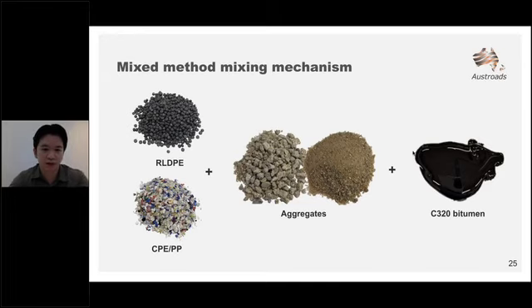Anyway, I'll jump right in. Just to recap, as we revisit these images, recycled LDPE and commingled PE/PP were selected for the mix method. Basically, the idea here is that upon contact, the plastics would melt and form a layer of coating over the aggregates, and some of them will stay as a solid part of the aggregates until hot bitumen is added into the mixing process and combined to produce the actual asphalt mix. And do note that specifically for the emissions test, each plastic was added individually to form specific blends. In no instance would we actually use 2 plastics at the same time to create an asphalt mixture.